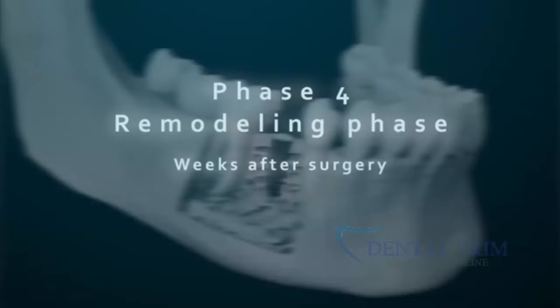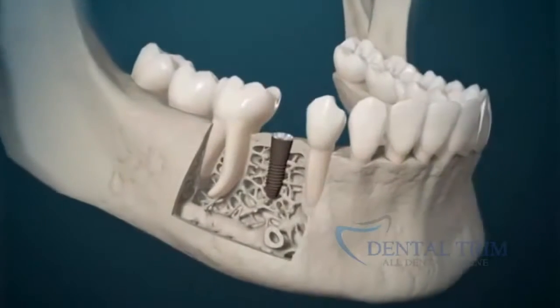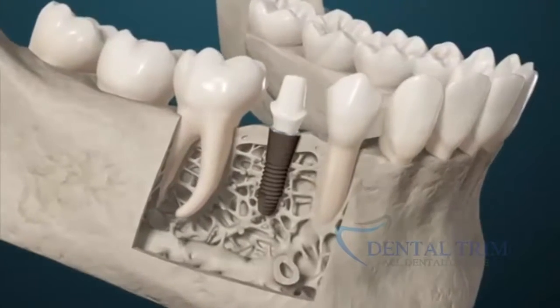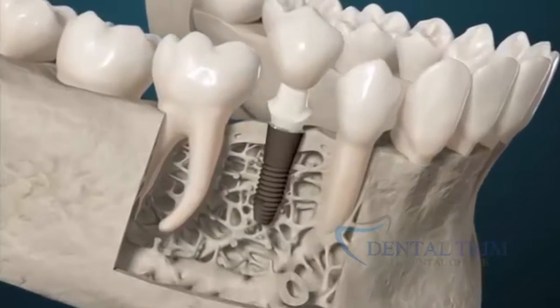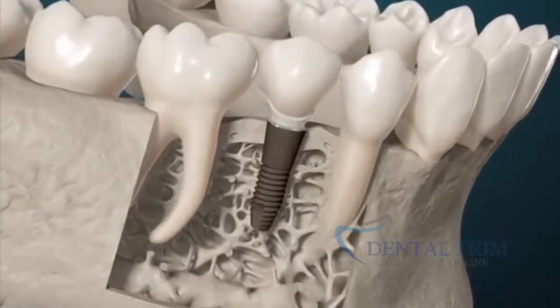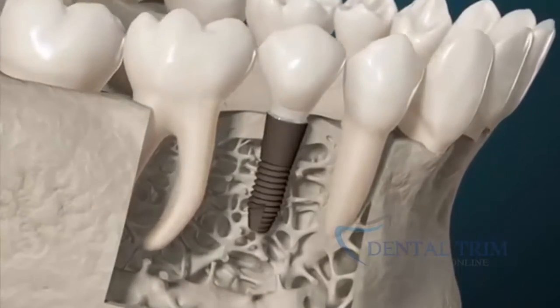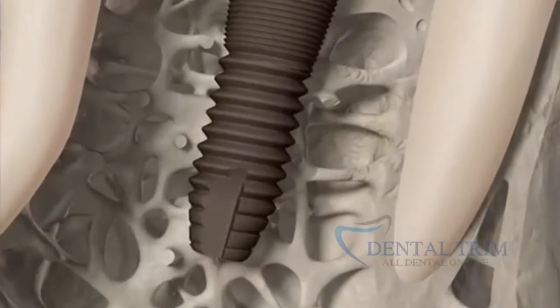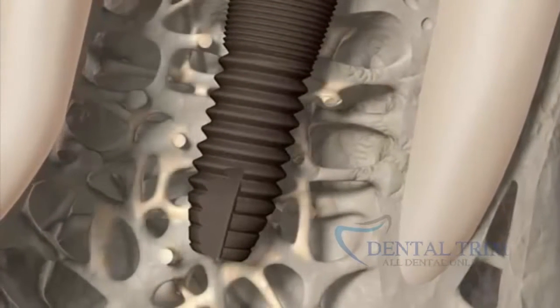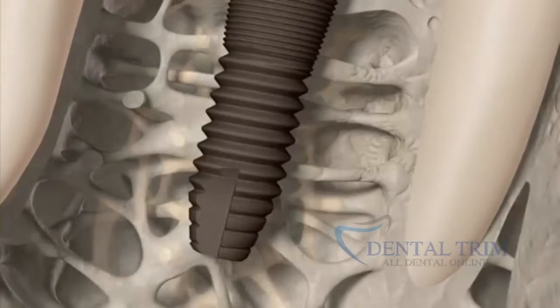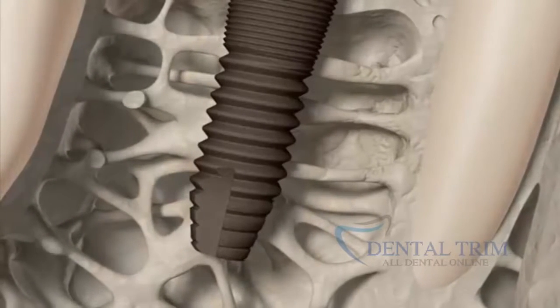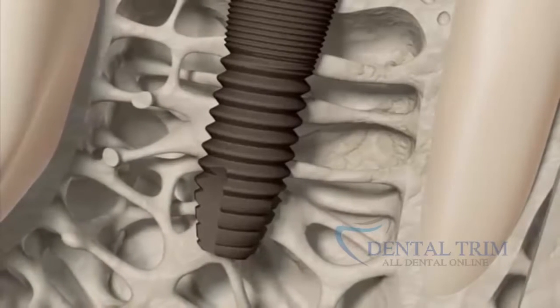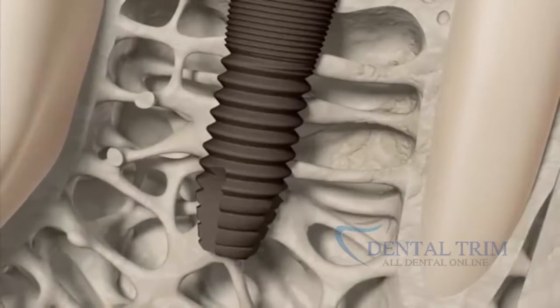Orderly and coordinated bone remodeling restores the stability of the site. Load adaptation is of pivotal importance: initially, woven bone grows in the valleys of the implant surface and parallel to it. After remodeling, most bone is structured perpendicularly to the peaks of the implant threads — at right angles to the implant surface. The architecture and organization of this bone becomes trabecular, directly responsive to forces imposed through the implant to the interfacial tissues.